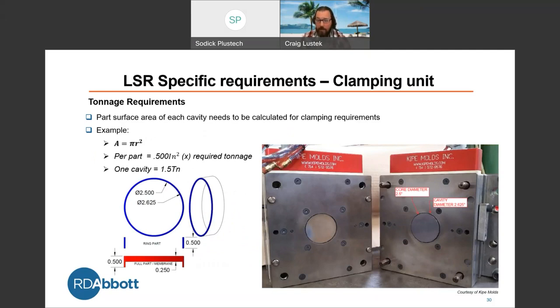So I'm taking that area and I'm going to calculate it by the higher number. I always go on my safety factor. So as you can see, just one cavity, we need 1.5 tons to clamp off properly on this one cavity. But you can see on the core diameter versus the cavity diameter, depending on the type of machine you have, you might only be able to fit so many parts within that molding parameter on your platen. So it's always good to know, again, from the tool maker, to calculate out and know how big you actually need that platen to be for your clamp force.